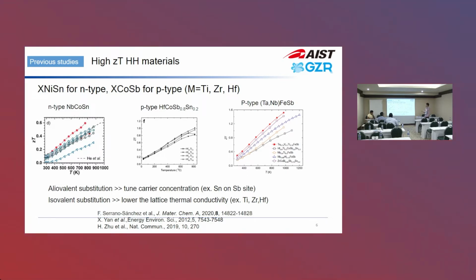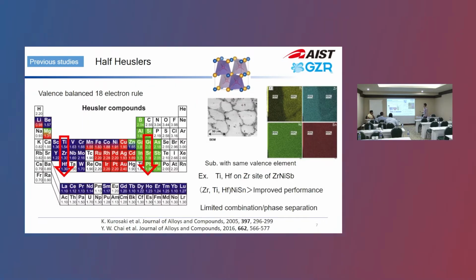Aliovalent substitution is used to tune the carrier concentration, and isovalent substitution is usually used for lowering lattice thermal conductivity. But one problem is you don't have many choices for alloying or substitution, because if you choose this row, you can only change zirconium to titanium or hafnium. That is effective, but sometimes you change the grain boundary situation, or you can get a phase separation in the matrix phases.